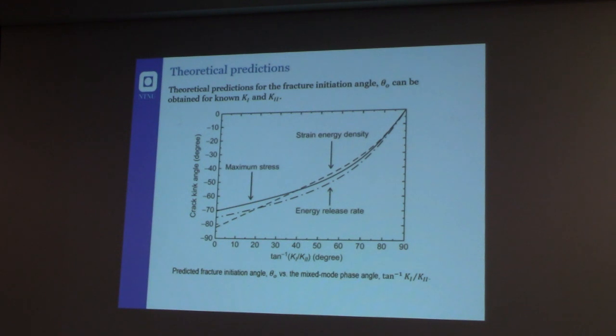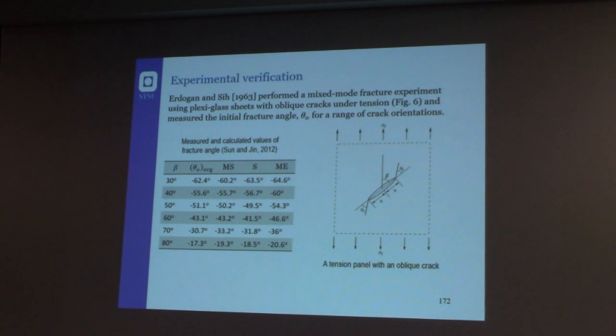After that, George C. Sih also improved the method, introducing a strain energy density approach that has two advantages. It's sensitive to the Poisson's ratio variation, and it is also insensitive to the mesh size. So this is a big advantage. But in terms of angle prediction of crack propagation, it is very similar to the maximum stress criterion. There is not a big difference in terms of angle prediction between the maximum stress criterion and the strain energy density criterion. They give almost the same value of the crack propagation angle. This table is reported in a book that is nowadays used for teaching, Sun and Jin's book, called Fracture Mechanics, published in 2012 by Taylor and Francis.